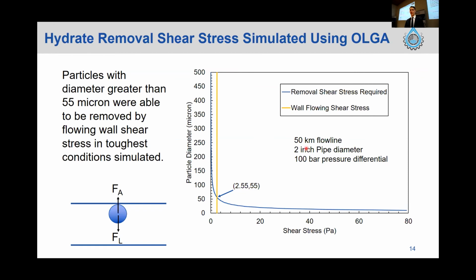And basically the findings for this nominal case was that hydrate particles with a diameter greater than 55 micron were able to actually be removed with the wall flowing shear stresses in that case without any AAs present. And it should also be noted that there was no consideration of moments or the rolling of those particles along the wall, which would also contribute to that removal.